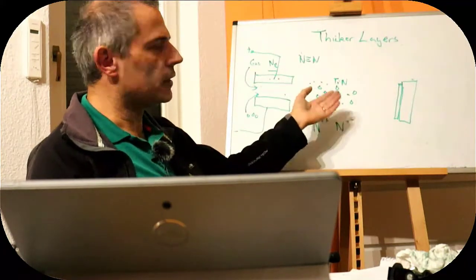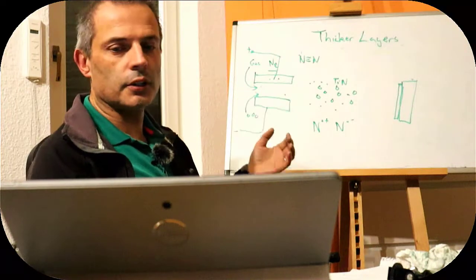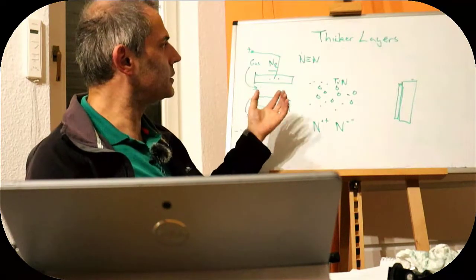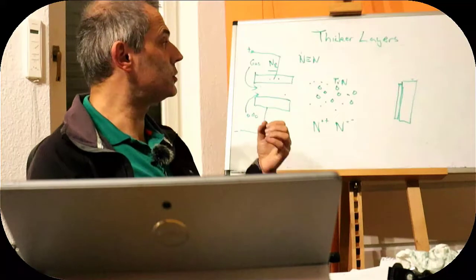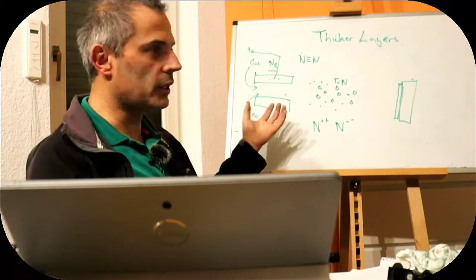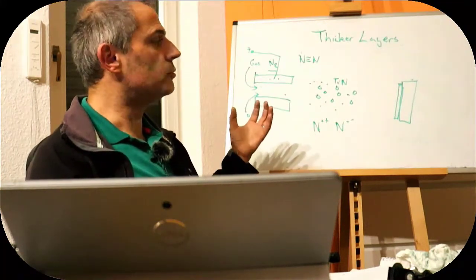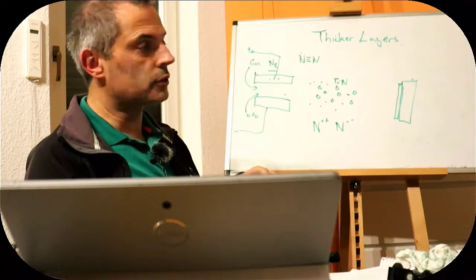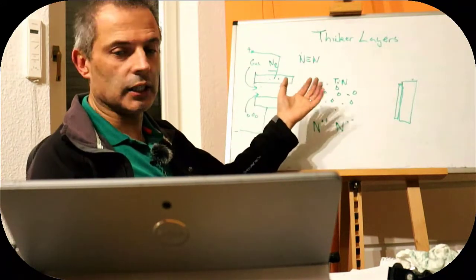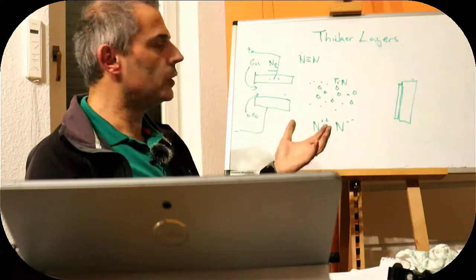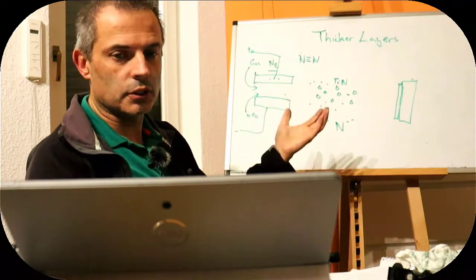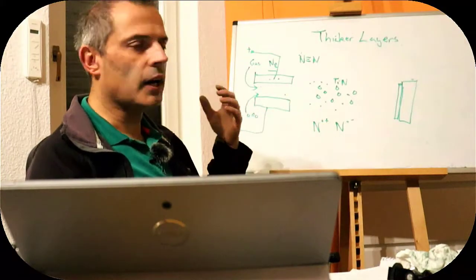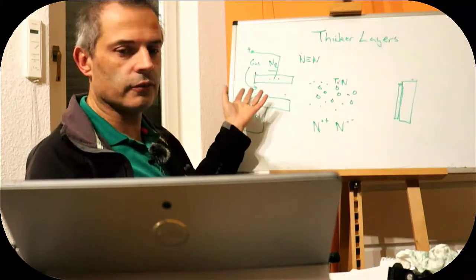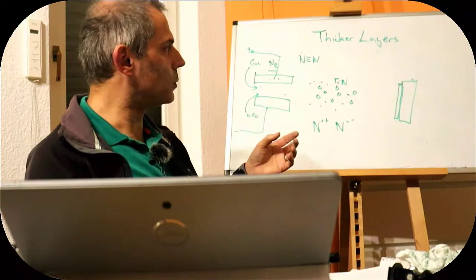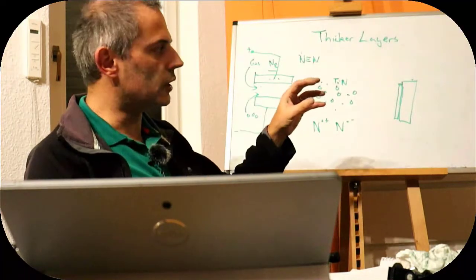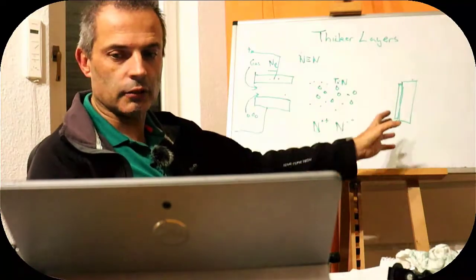Obviously, yes, if we're going to have a nitride, it would be good to have nitrogen in our chamber as the working gas. If we want to get up to really high temperatures, we're pretty much forced to have nitrogen and plasma as the working mixture. If we want a lower temperature, so if we want to, for example, generate a glass coating of silicon dioxide, we only need to get up to a few hundred degrees, 500–600 degrees, and then combustion is fine. We can do that with fire. We can easily get to the temperature required, and we can shoot little glass particles and generate a film.